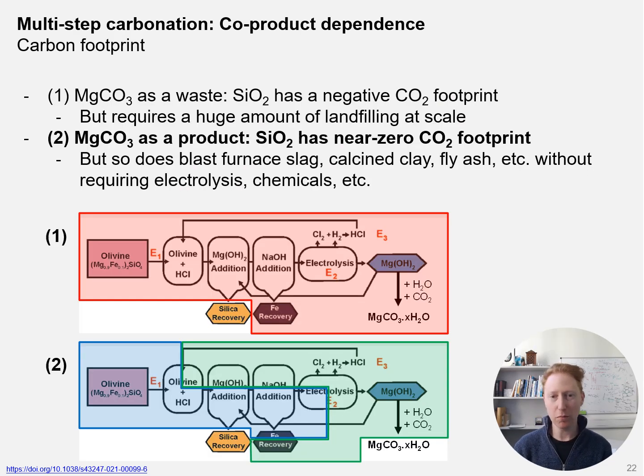Another aspect of the co-product dependence of multi-step CO₂ mineralization processes relates to their carbon footprint. To illustrate this, here are 2 ways that the allocation of CO₂ emissions from this process can be performed. The first way is that magnesium carbonate is treated as a waste. It is landfilled and CO₂ is stored permanently in the magnesium carbonate. In this case, the silica supplementary cementitious material has a negative carbon footprint. It is the only product produced, but we would require a massive amount of landfilling to produce this material at scale. This option is anyway impractical, since the majority of the revenue should be coming from selling the magnesium carbonate.